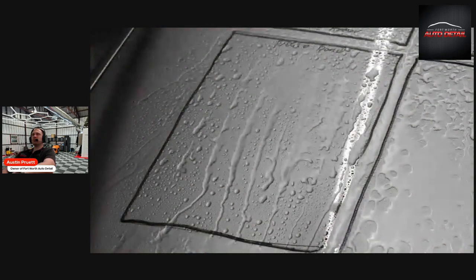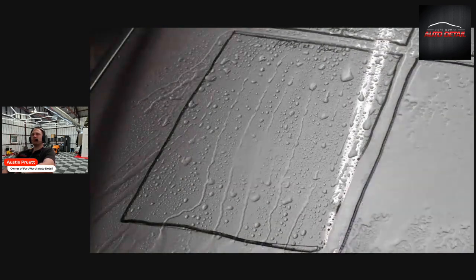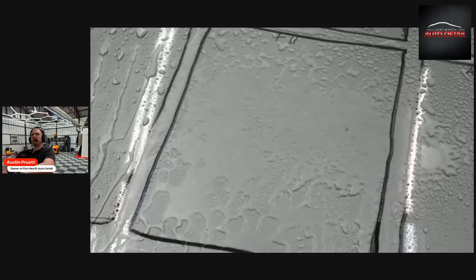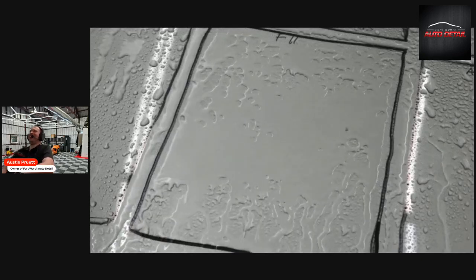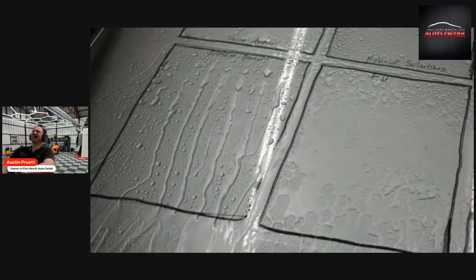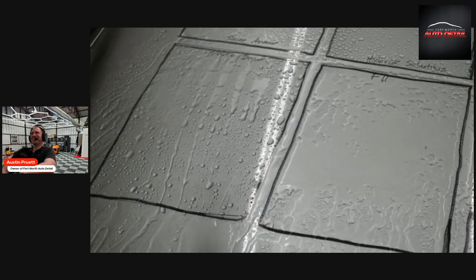And the Nanobond is still performing very well with the water forming beads across the entire test area. Unfortunately, the F11 is forming mostly a sheet across the test area. And the Nanobond is definitely performing quite a bit better than the F11 after exposure to the strip wash.